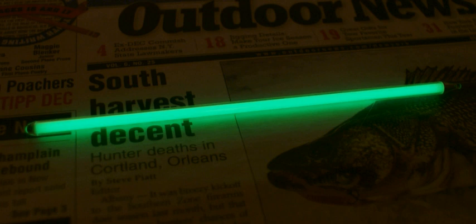Tritium lighting is made using glass tubes with a phosphor layer in them and tritium gas inside the tube. Such a tube is known as a gaseous tritium light source. The tritium in a gaseous tritium light source undergoes beta decay, releasing electrons that cause the phosphor layer to phosphoresce. During manufacture, a length of borosilicate glass tube that has had the inside surface coated with a phosphor-containing material is filled with radioactive tritium. The tube is then sealed at the desired length using a carbon dioxide laser.